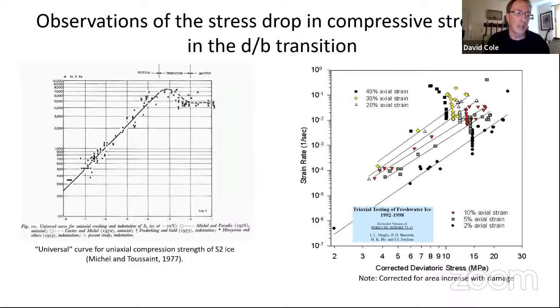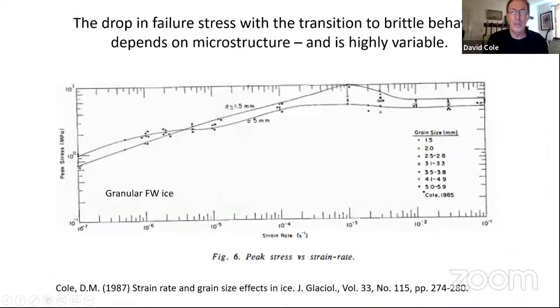One quick observation is this business of the universal failure curve for ice, and some of the analyses out there lean heavily on this decreasing strength with increasing rate. I've got to say, just recently, looking at a lot of the background data, this is not that well behaved of a process. If you look at, for example, the work from the Canadians on the damaged ice, this 40% damage at really high rates, you see a little bit of that. The axes are flipped, you'd have to flip the X and Y here. But you just don't see that fall off systematically. It's sort of there in a lot of data sets and sort of not there. So I have some misgivings about that.